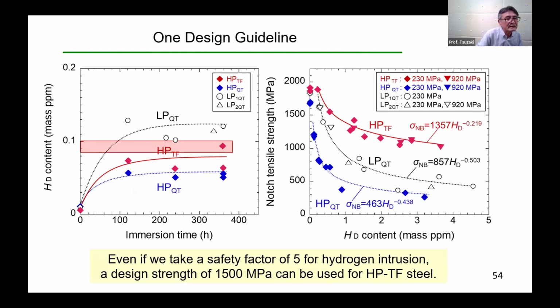Now, let us examine the relationship between the amount of hydrogen intrusion from environment, left figure, and the notch tensile strength, right figure. Even if we take a safety factor of 5 for hydrogen embrittlement, hydrogen intrusion, namely 0.5 ppm HD, a design strength of 1500 MPa can be used for HPTF steel. Of course, further research is needed, but I think this design guideline is very interesting.